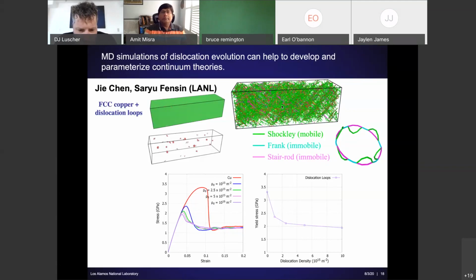I think so. Yeah, I think if you start from that kind of simplified analysis of Taylor, but instead replace, so they assume constant mobile dislocation density. If you replace that assumption with something associated with the nucleation of dislocations associated with that shock front, or some model that expresses how the dislocation state will evolve as the wave is moving through the material, then I think you could connect everything. I haven't done that, but I think it's an interesting idea. And if you have a model for dislocation evolution, there's no reason why you can't add some approximations or relationships about how the interfaces play into that.